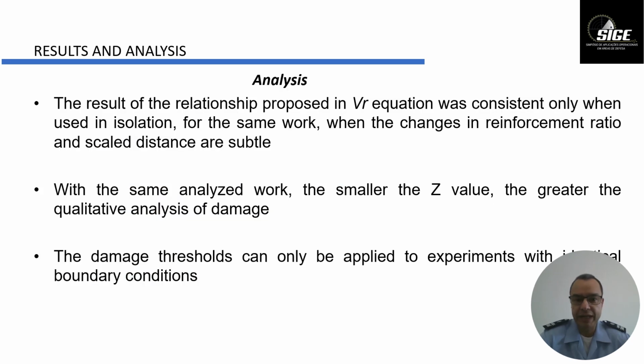What's important to see in the analysis is that the result of the relationship proposed in the reference value equation was consistent only when used in isolation for the same work, when the changes in reinforcement ratio and scaled distance are subtle. Within the same work, the smaller the Z value, the greater the qualitative damage. The damage thresholds can only be applied to experiments with an initial boundary condition, so, a similar boundary condition.